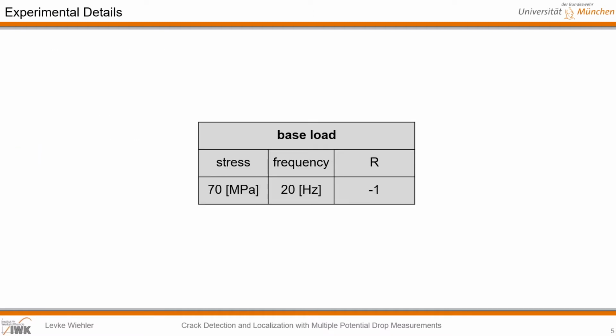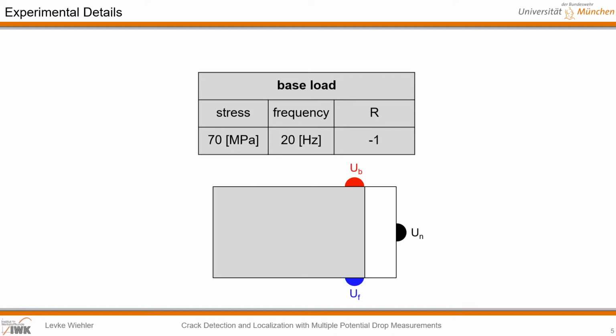Fatigue tests were carried out using a servo-hydraulic testing machine equipped with a Doli EDC 580 control electronics with the following baseload. In this study, single-edge notched specimens were equipped with 3 potential probes, on the front side, on the back side, and on the narrow side of the specimen. Secondary notches were lasered in the notch root to force crack initiation at a defined position.